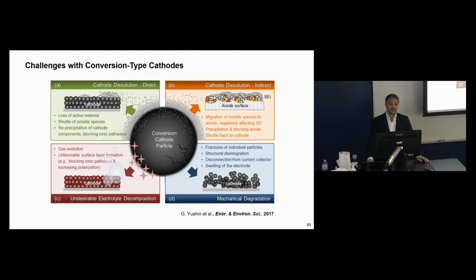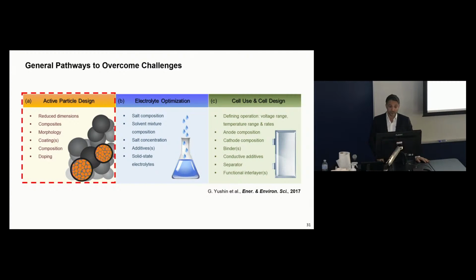It induces gassing, and also, unfortunately, all conversion cathodes, to some degree, dissolve during cycling. At some point of charge or discharge, they produce soluble species that dissolve. And that's a huge problem, right? You dissolve your active material, you also have precipitate on your anode, and the resistance of the cells keeps increasing. That's a huge problem. And so there are multiple solutions to that. There are multiple ways you can solve it at the cell level. You can do optimization of electrolytes. You can also design particles.